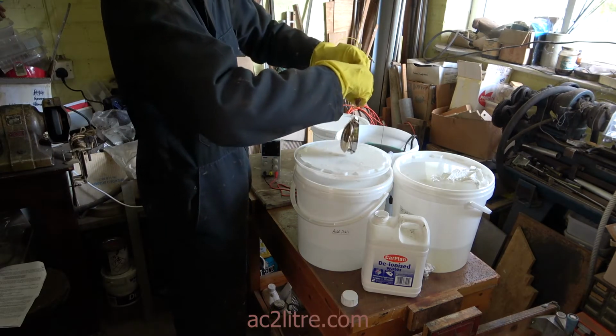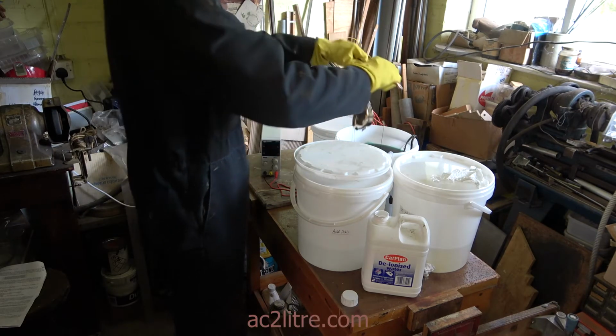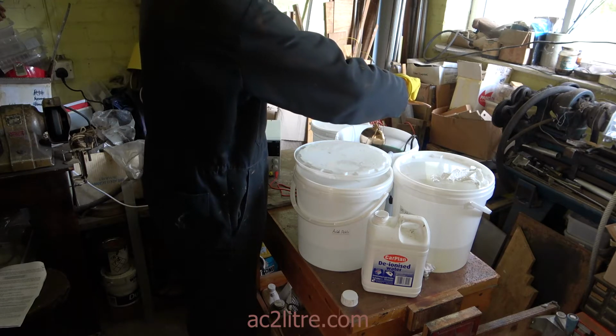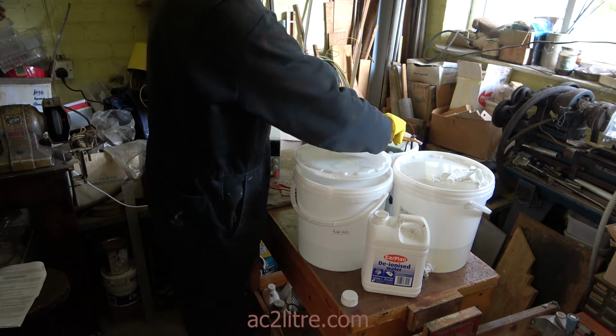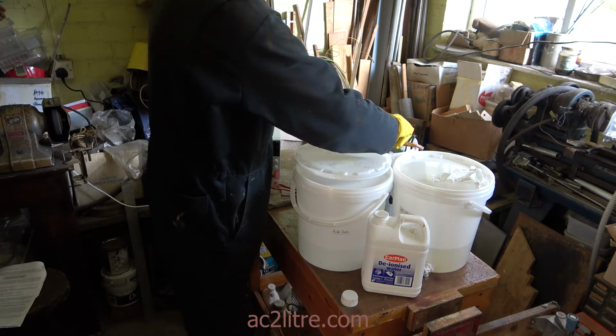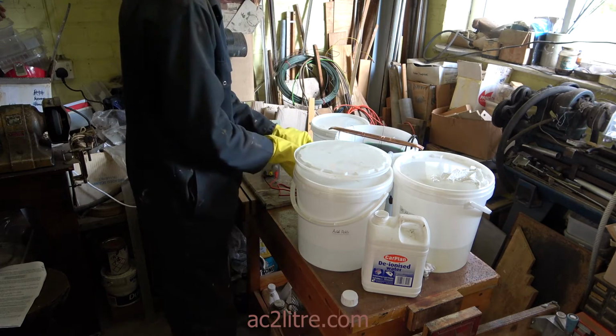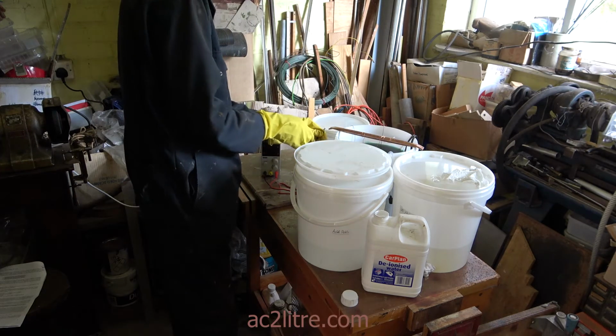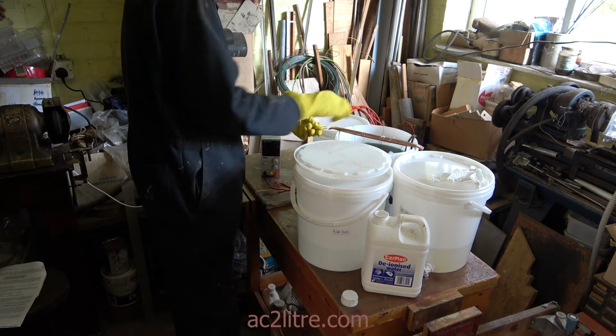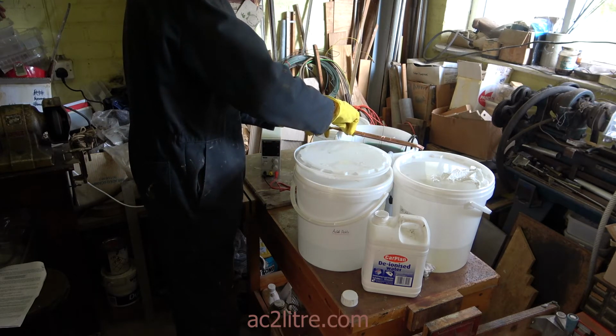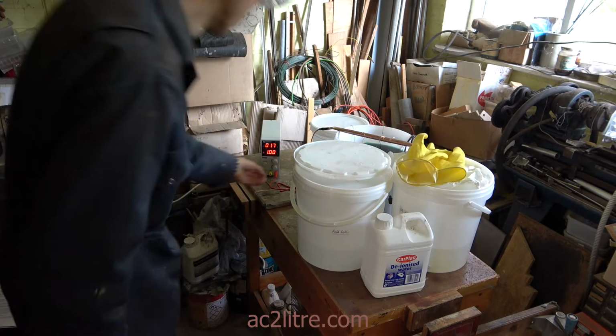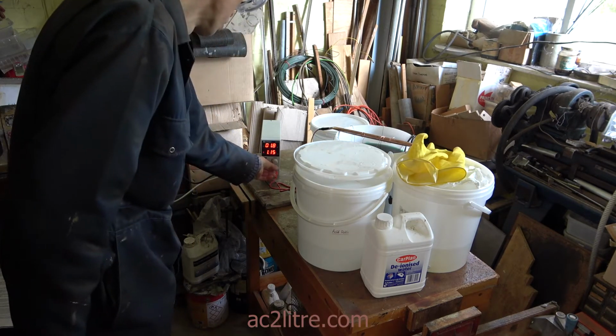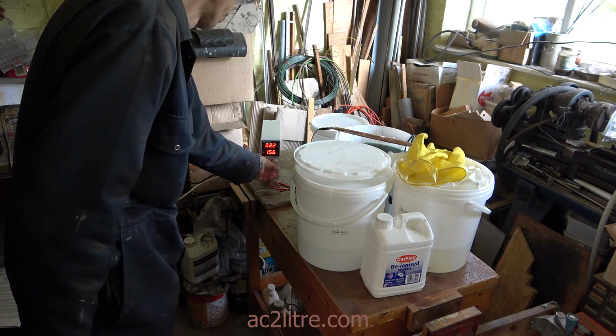Then it goes straight into the plating tank, which I've preheated to about 33 degrees C, and switch on the circulation pump. The negative of the power supply connects to the item being plated. As you can see, I hang the parts from a piece of copper pipe and thread copper wire around the component. The current is set to a figure worked out from the surface area to be plated. It should be 0.1 of an amp per square inch. That would be 15 milliamps per square centimetre. For brass items I plate for 30 minutes or so. For steel components I give it 50 to 60 minutes.